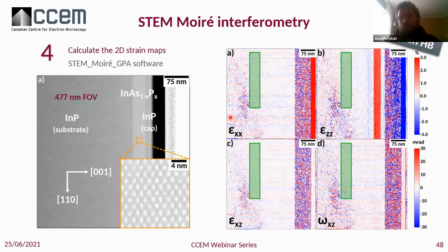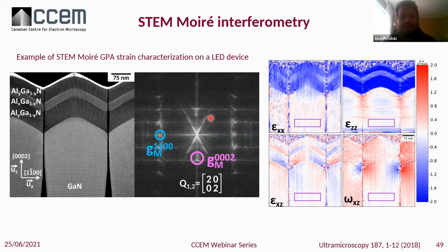Once you have that, then after you just do the classic strain map using the GPA algorithm, exactly the same thing. And this is what you get at the left. So 0 everywhere, as expected, except along the out of plane direction with the positive deformation in the middle. So a simple experimental setup, but a little bit of complexity in the processing. And that's what can be summarizing this type of method.